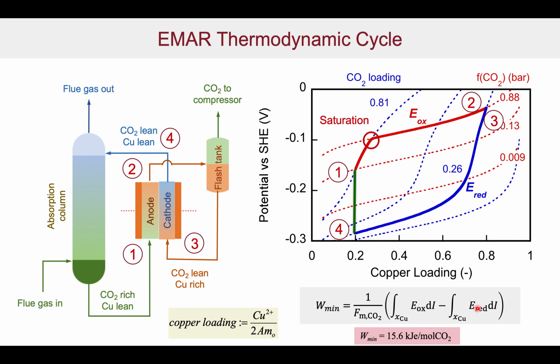I do want to point out that what we're interested in is how many electrons are required per CO2, or how many CO2s are released per electron. What you'll find is that initially it's not 100% because the initial electrons that are introduced in this region here are actually not being effectively used for releasing CO2 into the gas phase. It's because the CO2 is still retained in solution. So we don't expect to get really close to 100% Faradaic efficiency, but we can expect to get quite close to that.